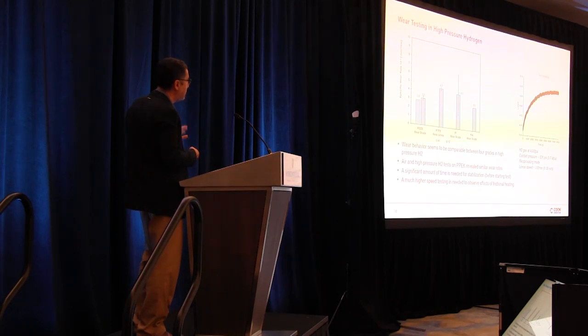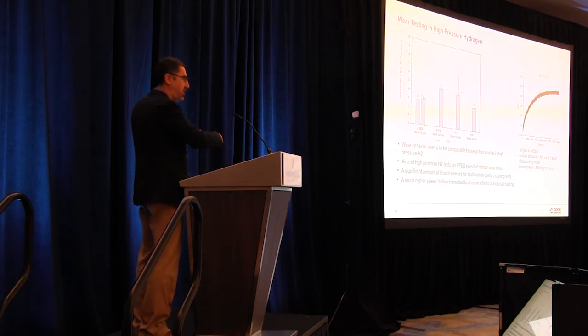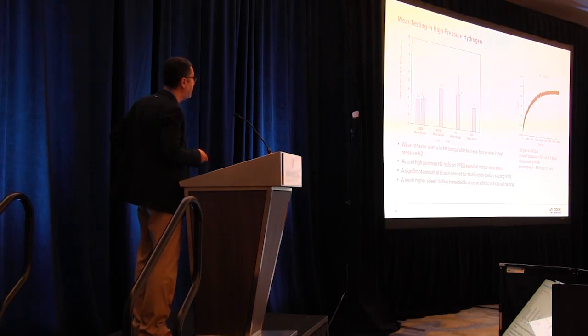So at these conditions, in this wear testing, it seems like the high pressure hydrogen is not affecting the wear behavior of the materials, and we are not able to differentiate any of these materials with respect to their tribological properties. But one important note is the linear speed we use, because of the limitations of the equipment we have. Note that it's inside the pressure chamber, so we cannot really go too fast with our motion. This is a very slow speed compared to what we find in compressors. And a slower speed generally does not make a lot of frictional heating, so it may be an important factor for this set of data. So with a higher speed wear testing, you may have a different result. So that's something we are working on.